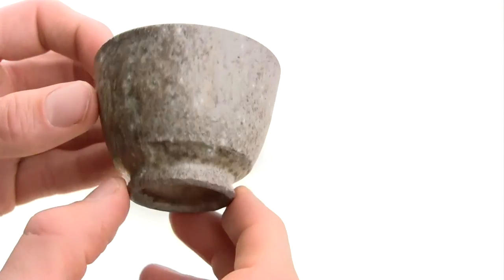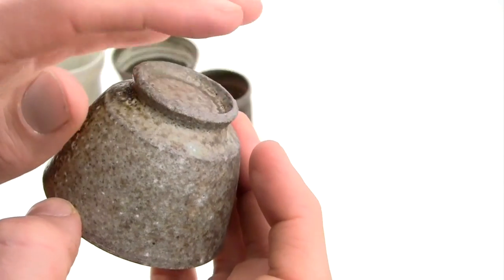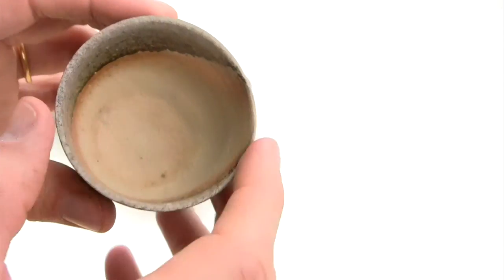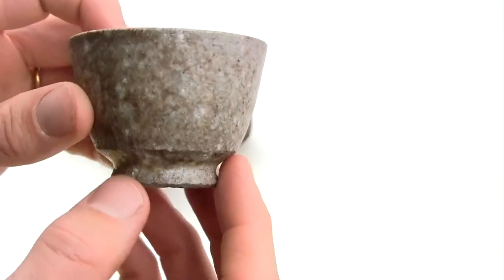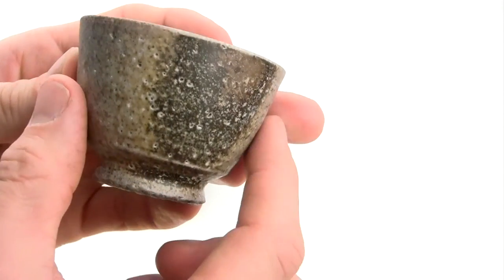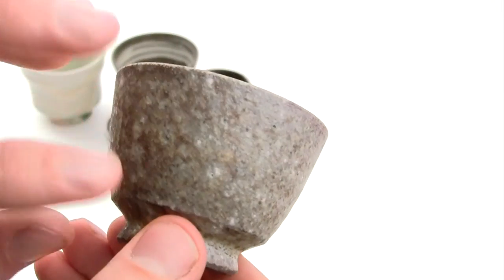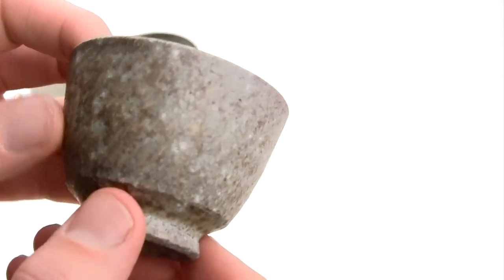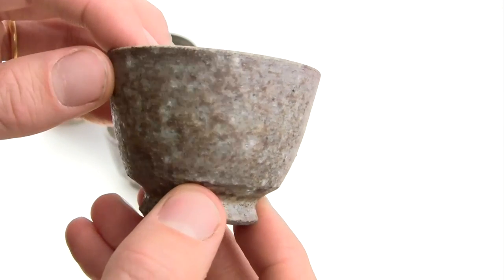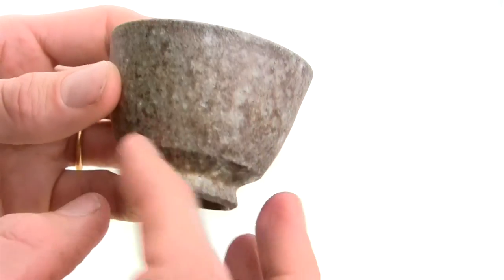This cup is a rather light stoneware clay, fired upside down in an anagama. You can see it's been glazed on the lower part as well, but not on the inside — making this interesting line on the inside, as the flame has moved in. But since it's been fired in the very front of the kiln, you can see how the flame has almost touched every part of the pot, at least on the backside — it's almost flown all the way around the pot before releasing. In this quite intense atmosphere at the front of an anagama kiln, the clay itself has started to be eaten away and you can see impurities in the clay coming forth, like these white stones here, making quite a lively landscape to look at.